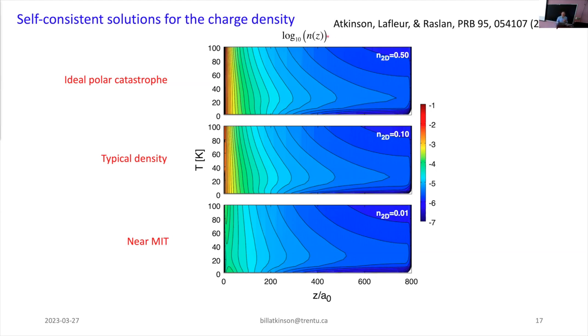And so these contours, I don't know if I said this already, this is the log of the electron density. So you can see that there's two components here. There's a component that's very strongly confined to the interface. This is quantum in the sense that it has a well-defined band structure. You can resolve individual bands. This has been seen in ARPES experiments. And then there are these tails that extend way into the substrate. And as you lower the total electron density, you can see that the interface component gets weaker and then eventually goes away. But the tails are there and they have this kind of universal structure.